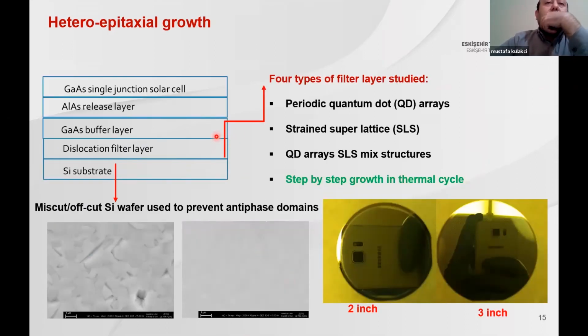So, in the research at the beginning, the important thing is what kind of defect filters or dislocation filters we should use to confine these threading dislocations so they don't reach the active device cells. So we have actually used 4 shapes. One of them is periodic quantum dot arrays between 5 and 10 periods. Also strained superlattices and a mix of superlattice and quantum dot arrays.